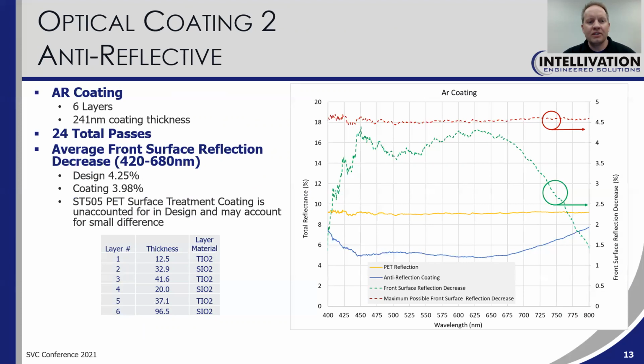The next coating we looked at was an anti-reflective coating. And so this was a 6-layer coating, 241 nanometer total thickness, so much thinner coating. And we used 24 total passes in this case. And so we were able to reduce the front surface reflection significantly. Our performance didn't quite match the design. We suspect that the surface coating on the polymer substrate probably explains the discrepancy between our design and our actual performance.